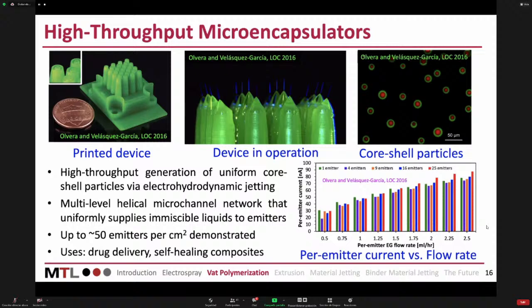And these devices are the first of their kind. The hydraulics are so complex that you cannot really efficiently make them in the clean room. We would be talking about many wafers to bond and many layers to transfer, and that would be just cumbersome. But with 3D printing, you can monolithically create this 3D structure, which in this case is these helical channels that make it possible to create the core shell particles. So, for example, the core can be medicine and the shell can be protection for the medicine. So you can ingest those particles and the cargo is protected from the digestive system, and then when it gets into the intestines, it gets released. And with that, you are able to give the dose, the drug, without having to inject the person or something along those lines.